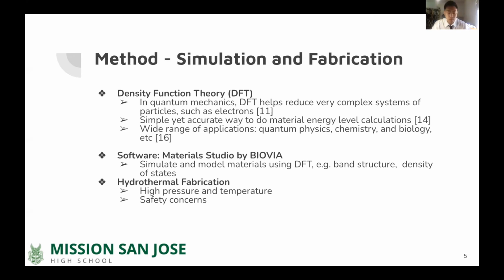For the simulation, we use the software Material Studio. And for the actual fabrication, we use hydrothermal techniques to create the nanotubes in the anode. The nanotubes are created in a chamber with very high pressure and temperature. One drawback of using this would be its safety concerns. Because it requires such high temperatures and high pressures inside the chamber, it must be kept very stable to prevent malfunction and explosions.